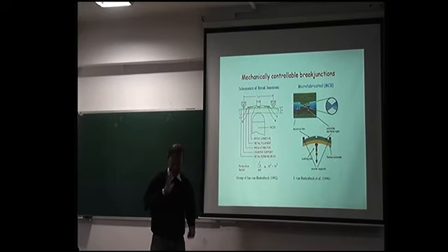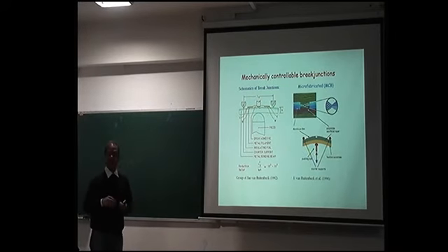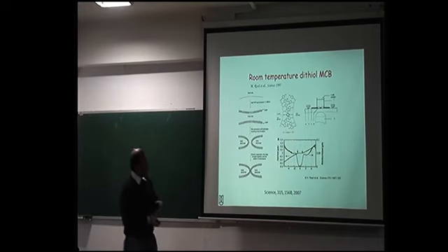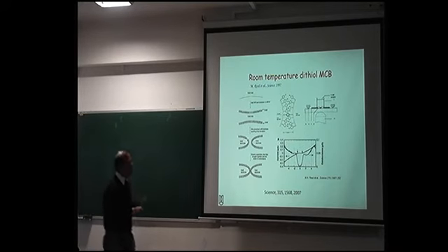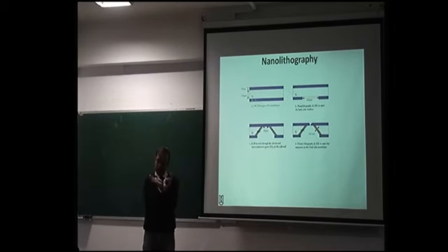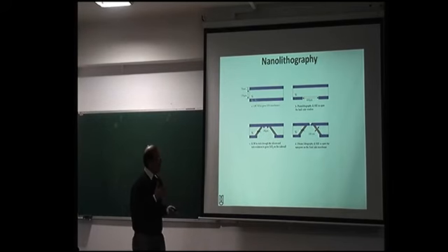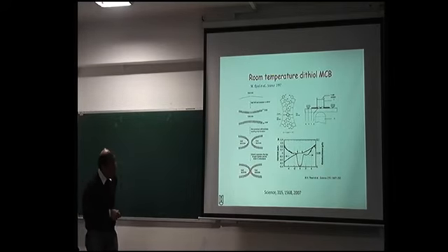But in the mechanical break junction, there is a little bit of controversy. That's why people are nowadays not using it, because some of the experiments could not be repeated. This is the first experiment. It is not done the way I said. The junction is made this way, but they put the molecule on both sides of the contact, and then again they tried to reduce the curvature so that a molecule-molecule junction reforms. That is the difference. But this created a lot of controversy, and people say there is actually an end-to-end molecule connection. Reproducibility is the biggest casualty here.